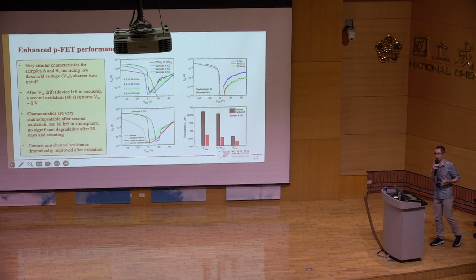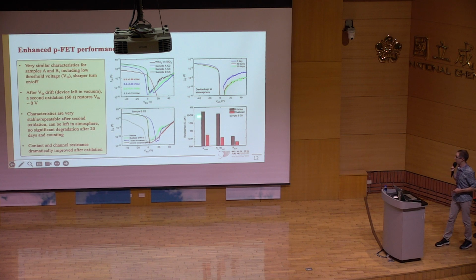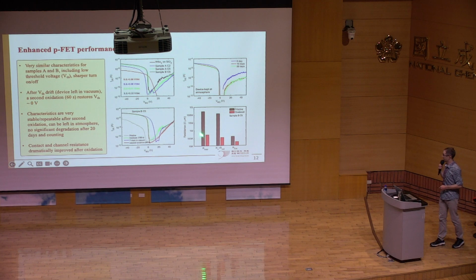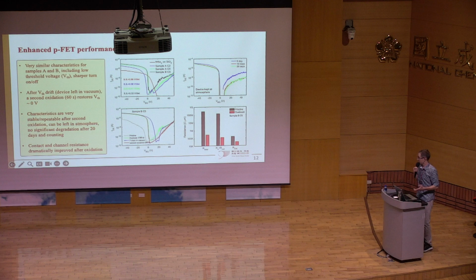And another way, really, just to quantify the quality of our devices is to measure the contact resistance. Before and after oxidation, the red bars are after oxidation, and we see that they're a lot lower. So again, we're achieving much lower contact resistance by this oxidation process.